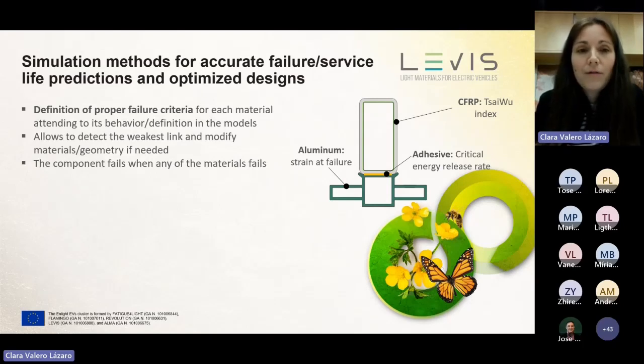So in this case, we have defined different failure criteria for each material, taking into account the specific behavior of each material. For example, if we have isotropic or anisotropic materials, failure is defined differently. So with this strategy, we can detect the weakest link in our multi-material components. So we can focus on the weakest part, and we can propose modification of the materials, geometry, and so on. Because when one of the materials fails, the whole component is considered to have failed also.